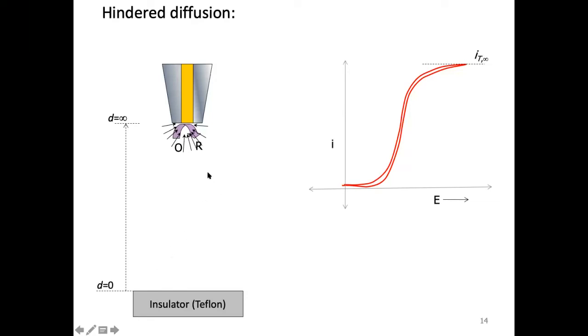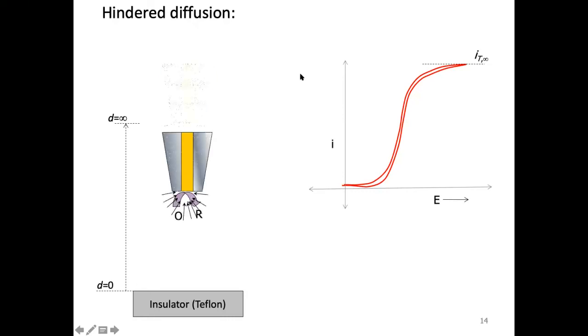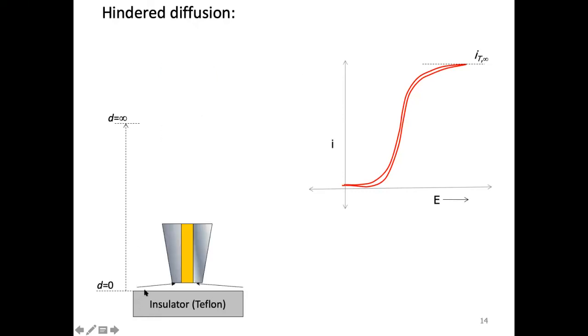Suppose I polarize such an electrode, which gave this kind of response, and somehow I bring this electrode closer to the insulating substrate, as close as a micron. Now there is a very small gap between my ultramicroelectrode and the substrate. My diffusion is hindered, because my species cannot enter the small gap. So it will definitely hinder, and obviously the current is going to decrease at tip distance zero compared to tip distance infinite.